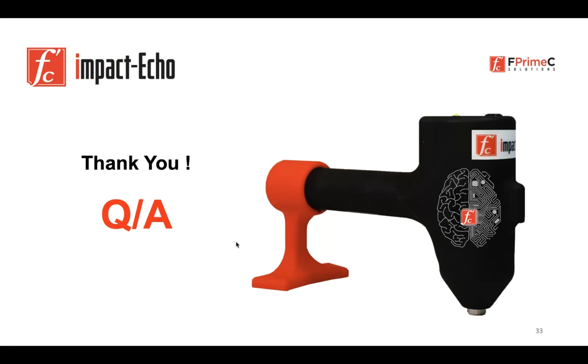How about geopolymer concrete? Again, it is possible to use the Impact Echo for polymeric concretes, but before doing any tests I strongly recommend doing some trials, because the P wave velocity in concrete in general practice is 4,000 meters per second in sound concrete. But that P wave speed will change based on the material, because it depends on the property of the material. So I don't know how much the P wave velocity is for those polymeric materials.